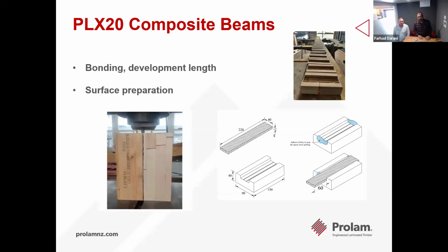So different development stages that we went through. First was actually how we want to glue the steel to the timber. So we used a high-performing epoxy, and we did different development length testing and surface preparation testing to make sure that we get enough resistance out of the connection between the steel and the timber. For example, this is a development test that we did in Sion to come up with the best surface preparation and measure the shear strength that we get at the surface between the steel and the timber.